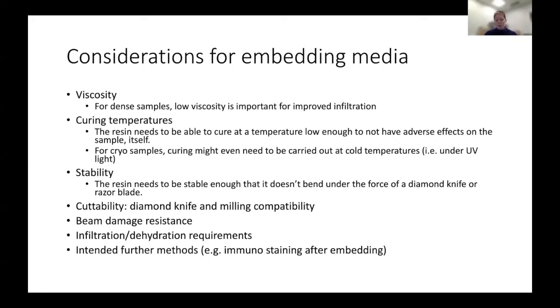Some resins also have different requirements for dehydration. Some resins are water miscible and some are not. And the ones that are not water miscible require dehydration of the sample before you can infiltrate. Otherwise, you'll trap water inside your sample. Resin won't get all the way in there and you'll have poor infiltration. Also, if your protocol requires further methods like immunostaining of sections, you can choose a resin that will optimize for immuno-EM. There are a few that are known for not masking antigen sites the way that some resins are.